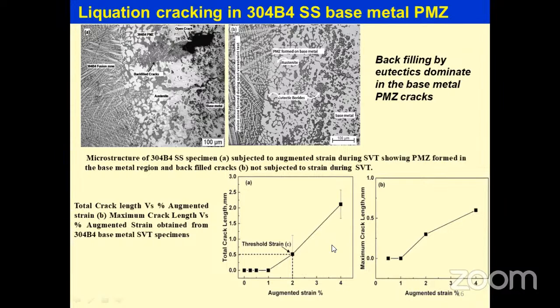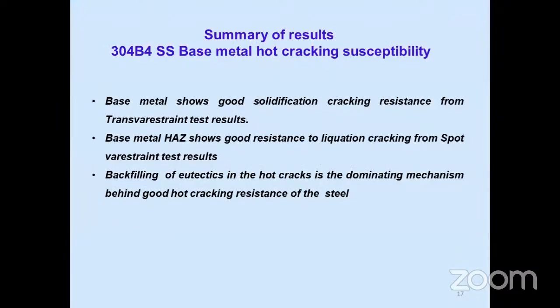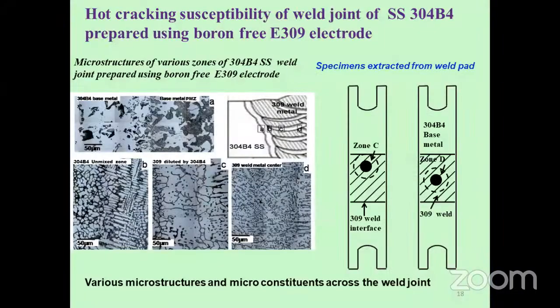So in that case, we say that borated stainless steel base metal is immune to hot cracking. This is in line with what we have found in the literature also. So we see that the borated base metal has good resistance to liquation cracking as well as solidification cracking, and this is because of the backfilling of the eutectics happening in the base metal region.